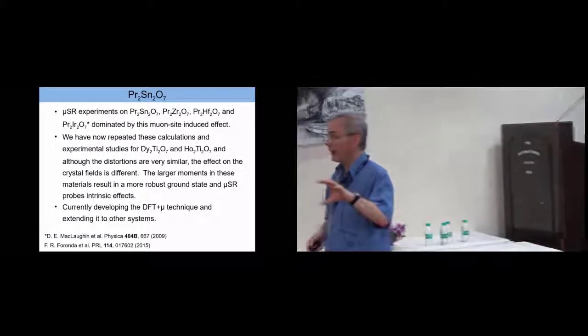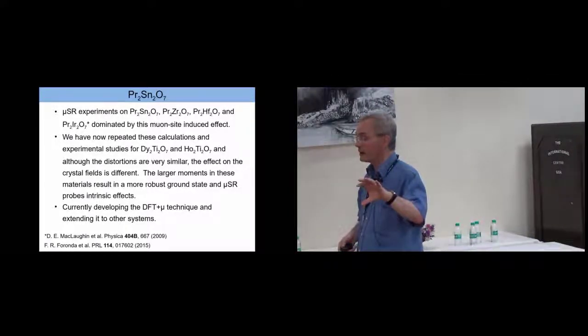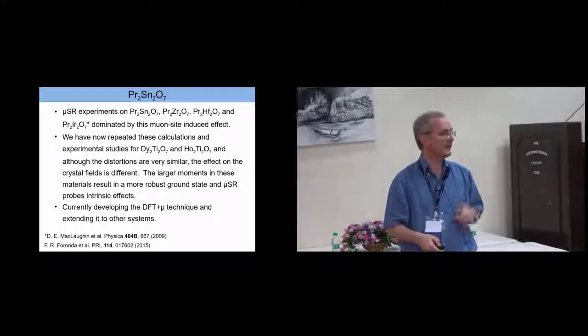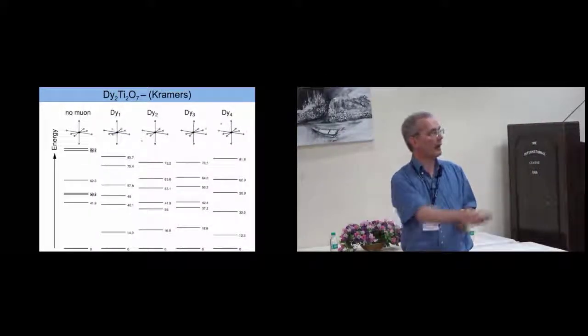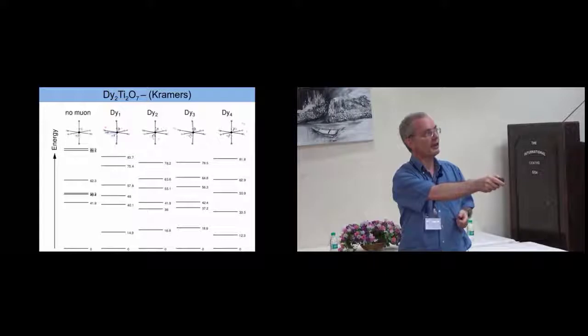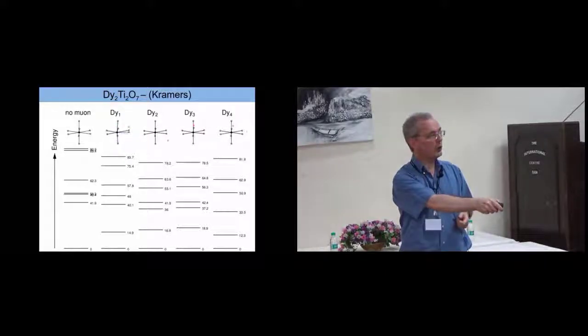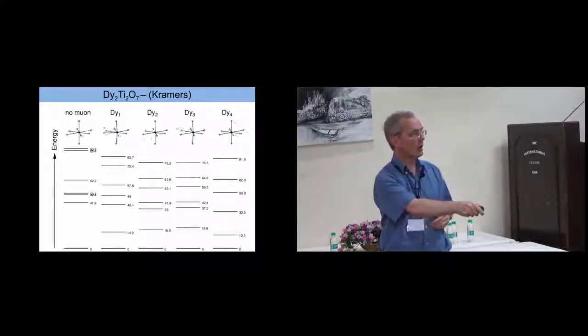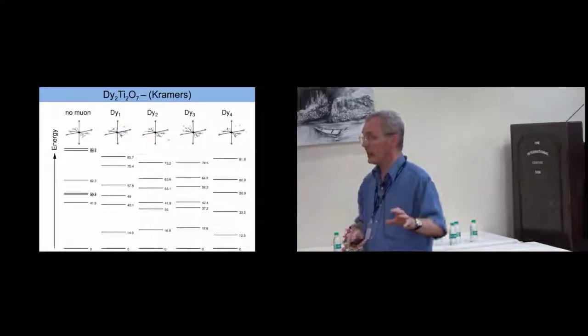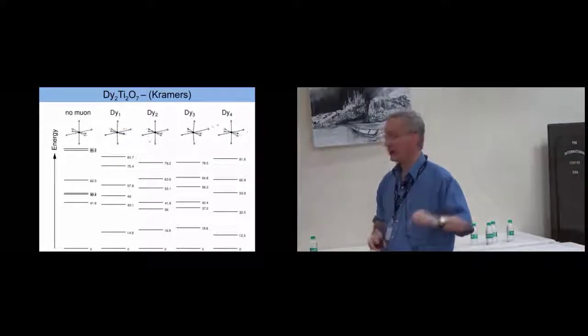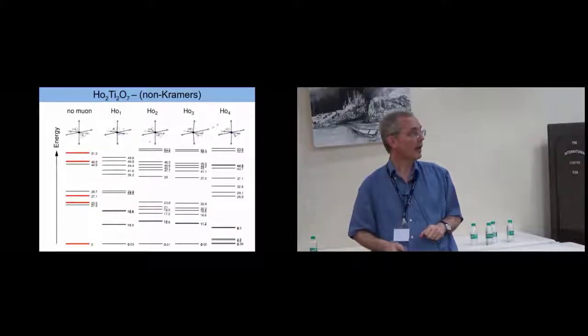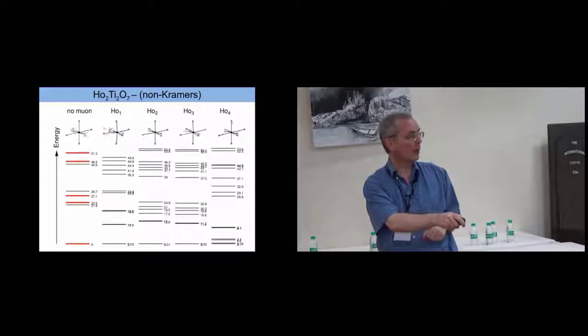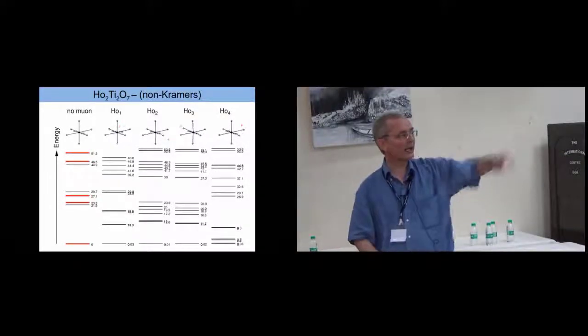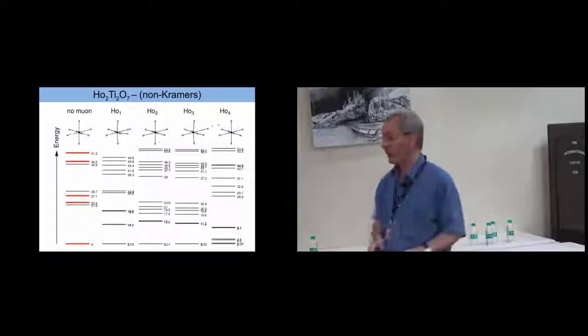Now, we've repeated these calculations for other spin ice materials. I'm not going to go through the details of this, except to say that when you do that, for example, in dysprosium titanate, this has a Kramers ground state. So although you change the excited state levels, the ground state remains a doublet. So in dysprosium titanate, this effect doesn't occur. In holmium titanate, it is a non-Kramers ground state, but it turns out the matrix elements are such that you don't really split the ground state by very much. So in holmium titanate, everything is fine.